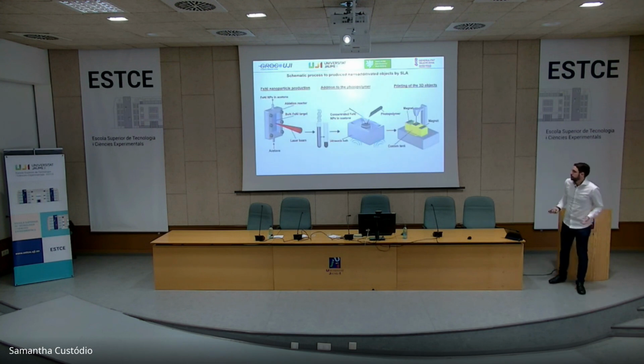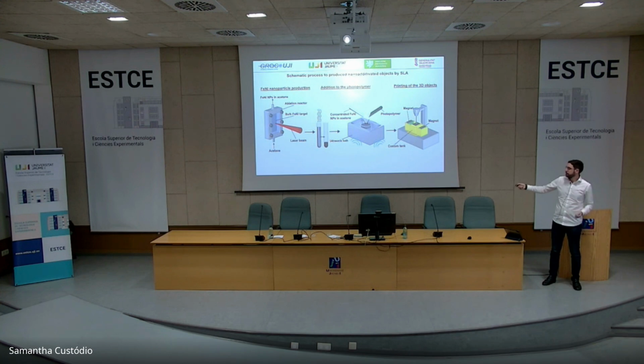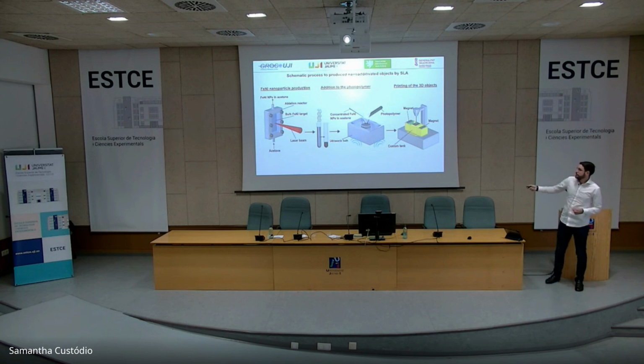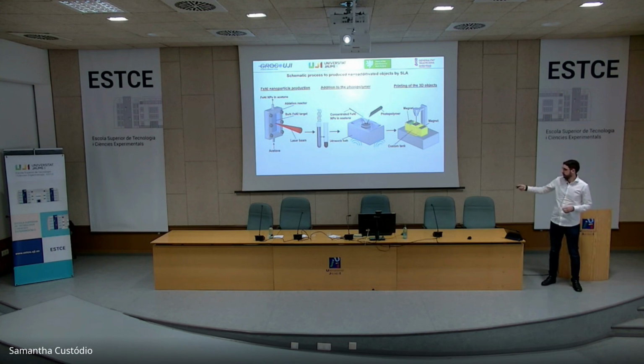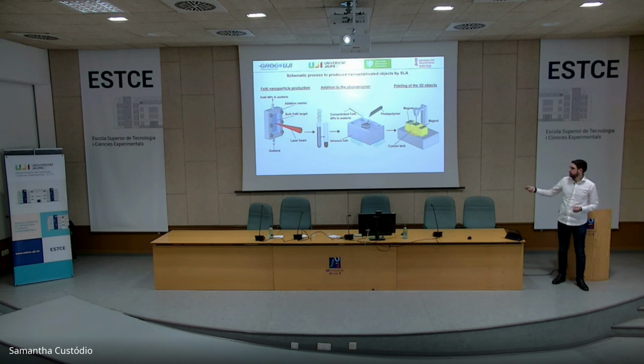So here, what do we do? We just take our chamber. We have some iron nickel. We chose this material because it has high magnetization. We just produce iron nickel nanoparticles in acetone, in this case, an organic liquid. We increased the concentration a bit to limit the amount of acetone that was in contact with the photopolymer. And we just do the mixing of these nanoparticles with the base photopolymer that is used in stereolithography.